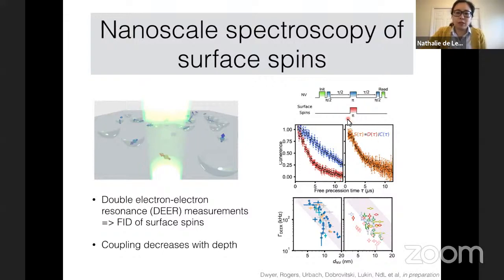And we can do this to read out what the coupling strength is to these surface spins. What we find is that, in general, this coupling strength decreases with depth with some scaling, which really tells you that these things exist at the surface. And we can prepare different kinds of surfaces that have different densities of these surface spins, where we have higher coupling for all of these points. And here we have lower coupling rates on average if we try to suppress this density.